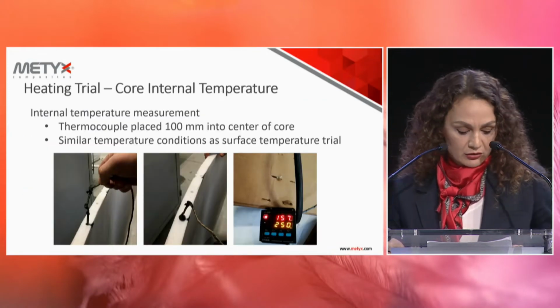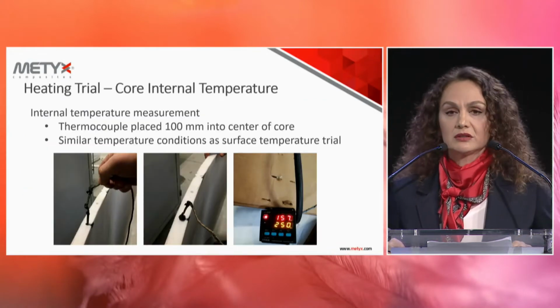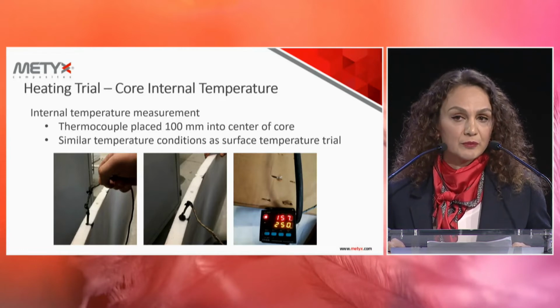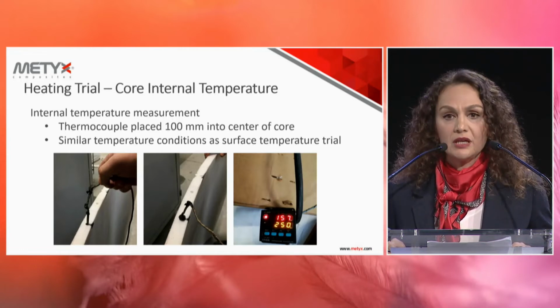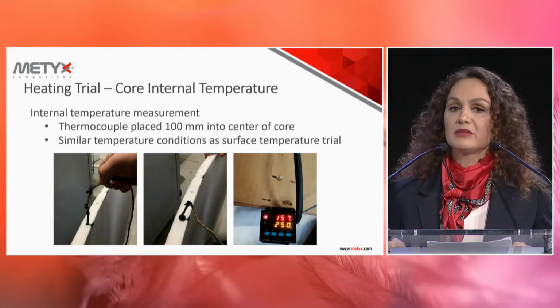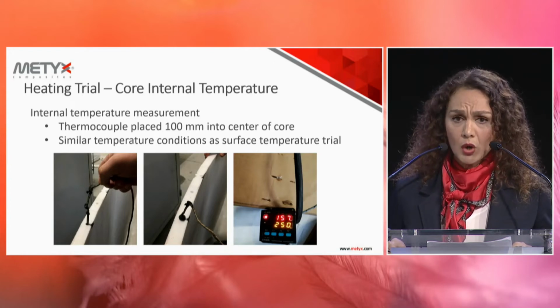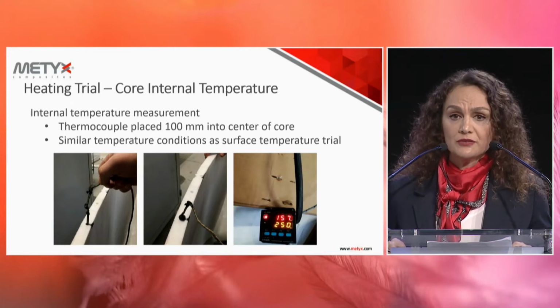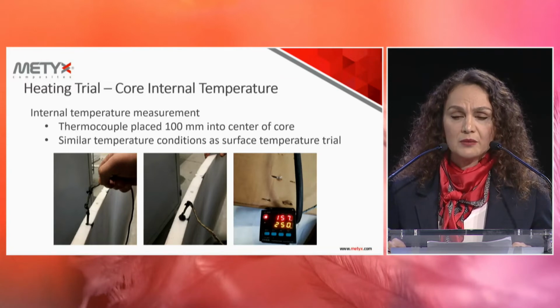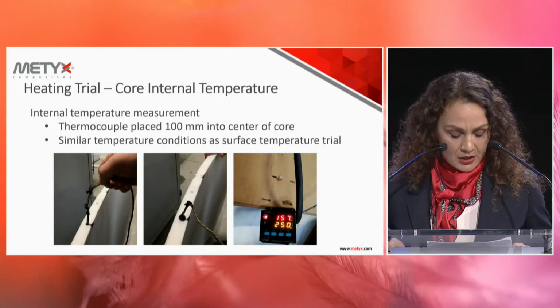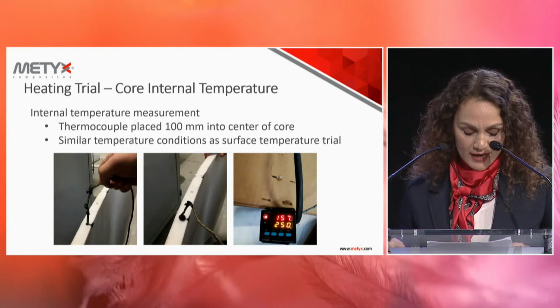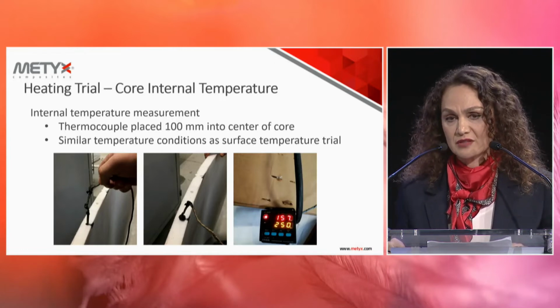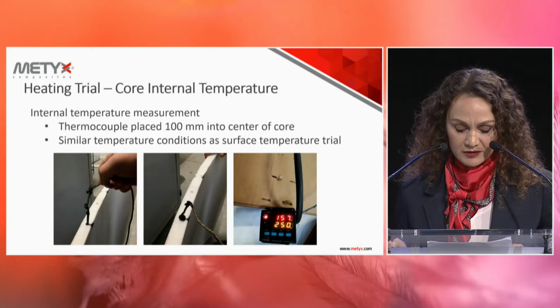Not only external temperature, we need to monitor internal temperature also. To do that, we drill a 100 millimeter hole into the center of the core, and then we place a thermocouple to measure temperature. We apply the same basic temperature conditions as we did in the external temperature trials.